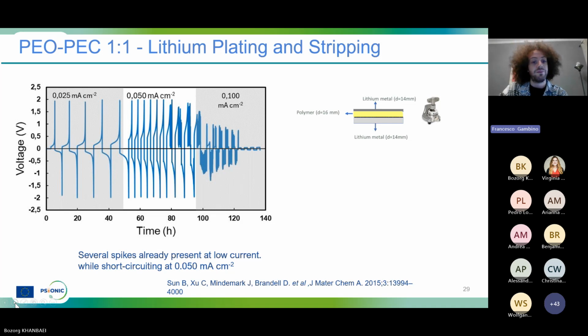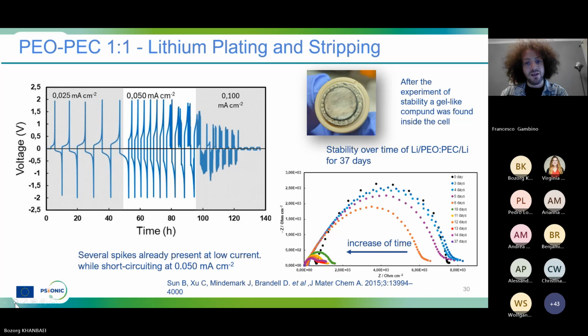However, at 40 degrees there are several spikes already at 0.05 milliampere per square centimeter, and when the current density was increased, the cell completely short circuited. Next, please. So we opened the cell and we observed a gel-like compound around the disc.